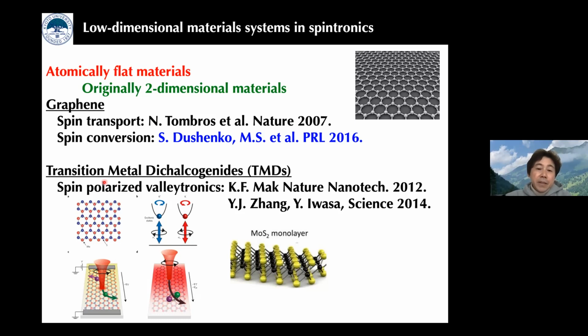The second important material is transition metal dichalcogenides, TMDs, because spin-polarized valleytronics can be established by using these material systems. In fact, Kin Fai Mak and co-workers reported the polarized light emission from single-layer MoS2, molybdenum disulfide monolayer, by using the spin-polarized valley state. Soon after that, a group at the University of Tokyo reported the reciprocal effect. Namely, they injected circularly polarized light into the single-layer MoS2 and observed the valley-dependent Hall effect.